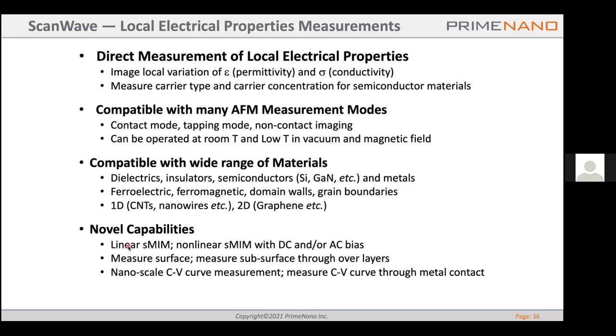It can operate as linear sMIM, directly measuring the sample. And also you can apply DC and AC voltage to do nonlinear measurements to get the dC/dV image and also get the CV curve at nanoscale. It can measure the sample surface and also measure features beneath the sample surface, such as dielectric layers, and it also has nanoscale CV curves that can measure beneath the surface. And also for semiconductors, you can use the wire connection as an extension of the probe to measure properties beneath that metal layer.